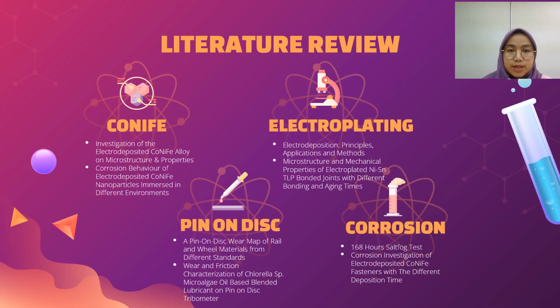There are many previous studies related to this project. In this literature review, the previous study is divided into 4 parts according to the keywords related to this study, which are CoNiFe, electroplating, pin-on-disc, and corrosion. From a study related to CoNiFe coating, the result for wear test showed that CoNiFe coated sample presents wear index of 0.003913 mm³ per Nm, which is less 13% by non-coated mild sample.